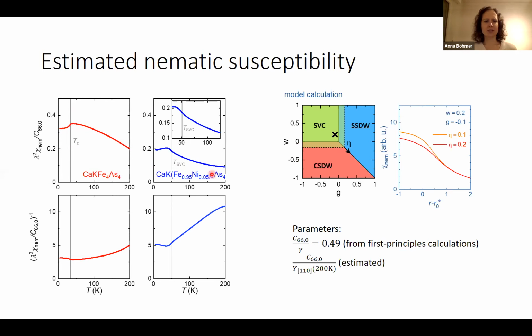The nematic susceptibility in our doped 1144 increases in a Curie-Weiss-like manner, but is far from critical. Remember, this has to be 1 at the transition, so we are much below that. Then at the transition, there's this subtle anomaly that almost looks like an inflection point, or rather, it does look like there is an inflection point here. And it's tempting to compare that with our model calculation, where in the case of a finite eta field, which we have in these compounds, there is also predicted to be an inflection point of the nematic susceptibility at the transition here. So to make the connection becomes tempting.